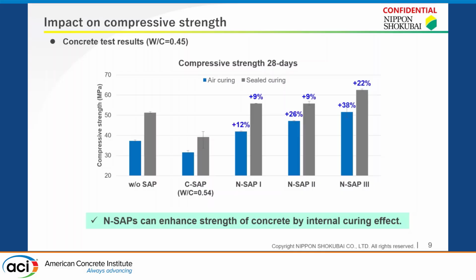And this data shows the relationship between increase in strength and absorption amount of new SAPs. So this suggests our new SAP can act as an internal curing agent in concrete.